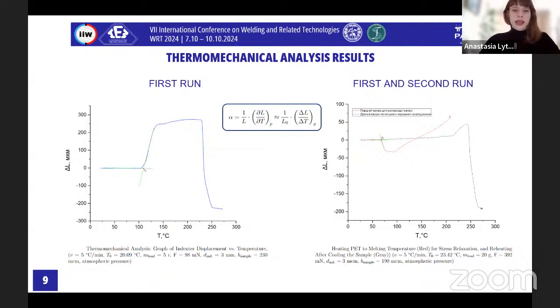Next analysis was thermomechanical analysis, and in the graph on the left, which shows PET before processing, the stress in the sample begins to increase at approximately 103 Celsius degrees due to residual plastic stresses within the material, as PET has shape memory. So at 103.80 degrees, the curve levels out. It's indicating that the thermal expansion of the sample is balanced by the applied load, meaning the sample is in equilibrium until around 240 degrees. To be more exact, it's 245 degrees, and it determines the melting temperature. It's the point where the indenter fully penetrates the sample, signaling complete melting of the material.